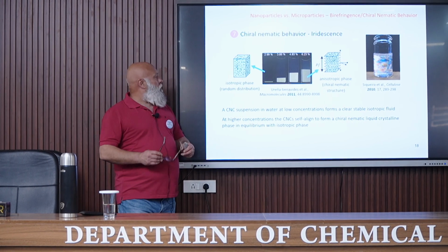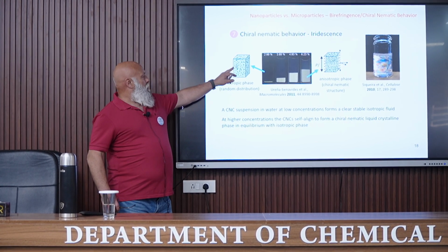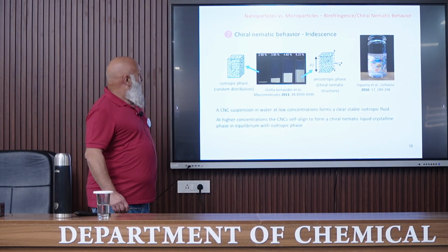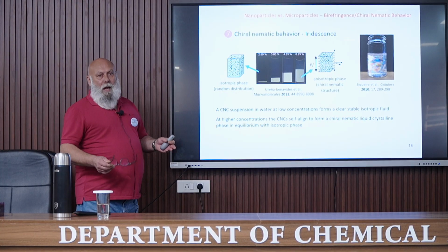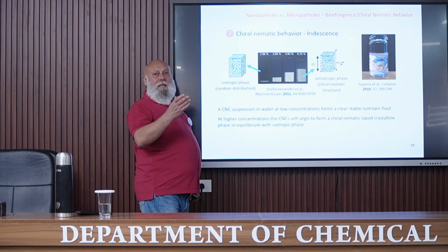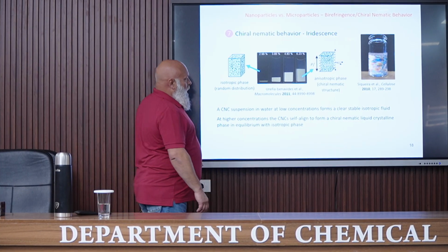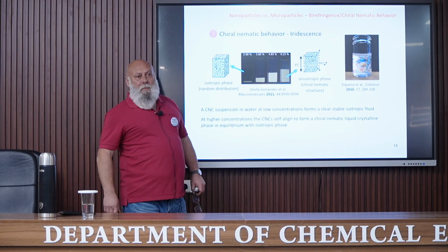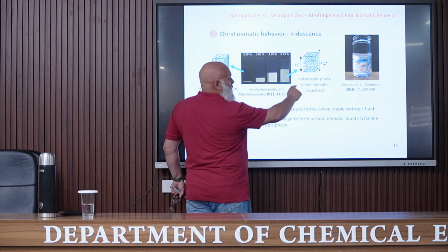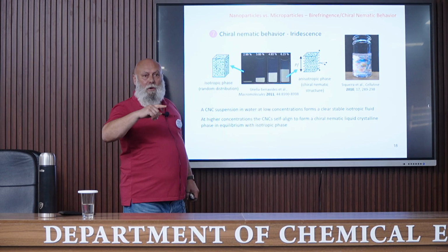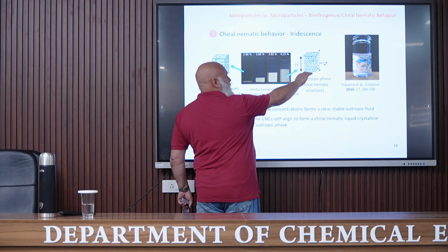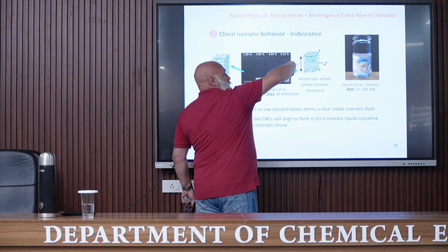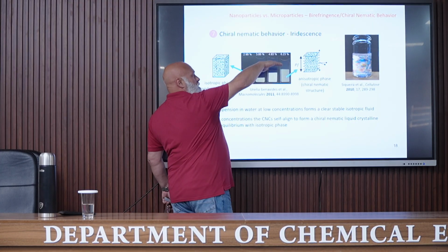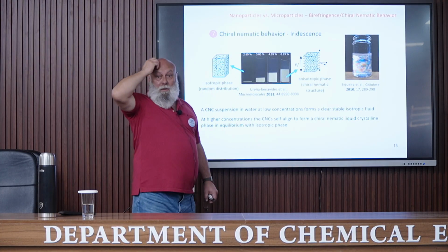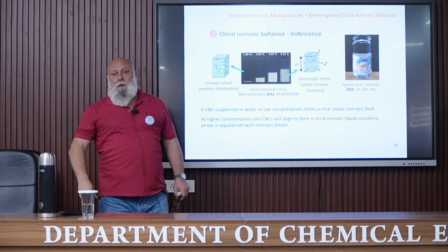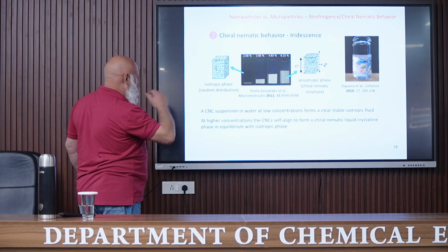In fact, when using a dilute suspension, we have an isotropic phase, meaning that there is a random orientation of the nanorods. From a given concentration that depends mainly on the aspect ratio of the nanorods, we have some organization or self-assembly of this nanoparticle, leading to what is called a chiral nematic structure. This phase, which is observed here, consists of an alignment of the nanorods in a given plane of the suspension, and then for the upper plane, we have an orientation, but with a shift in the orientation of the nanorods, and so on. And when we recover the same orientation, this distance is called the pitch of the dispersion. Okay, so it's the pitch of the helical structure.